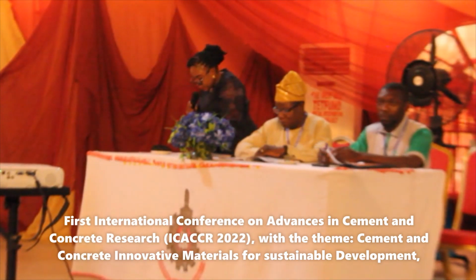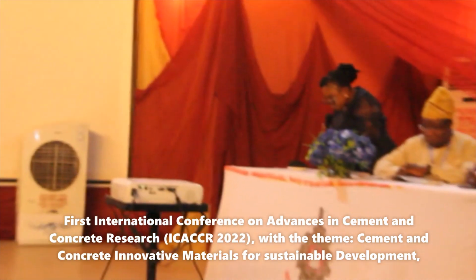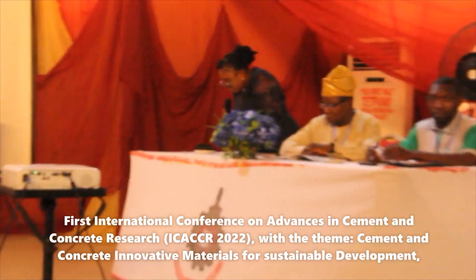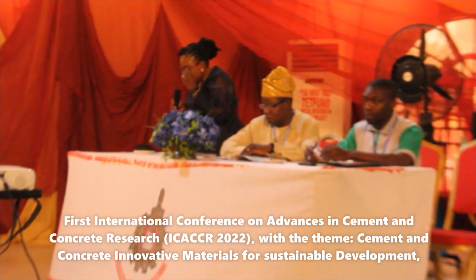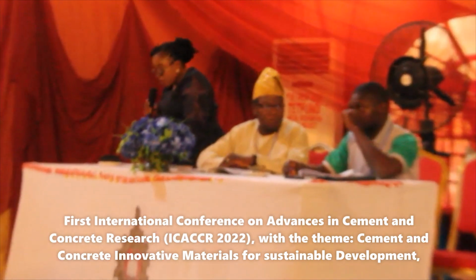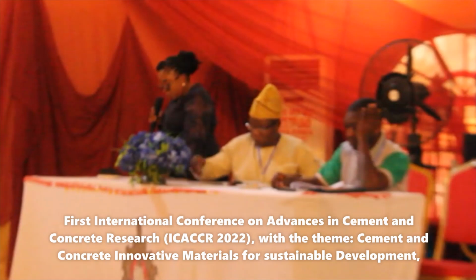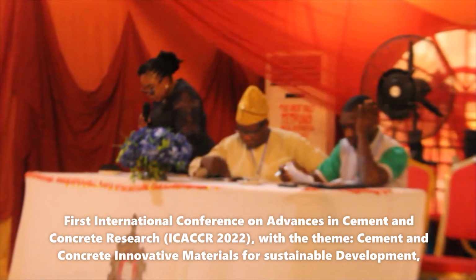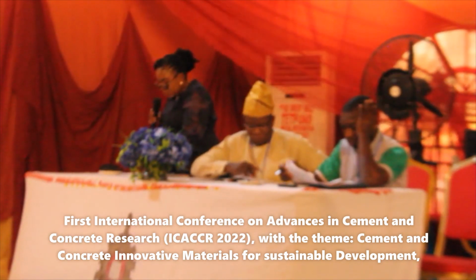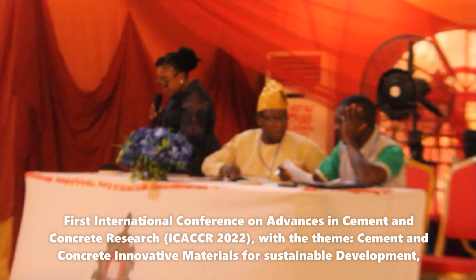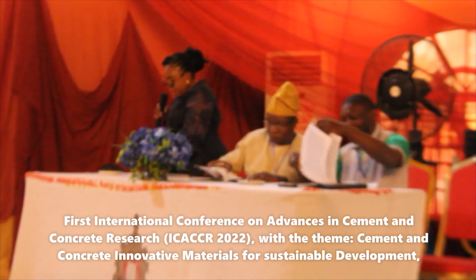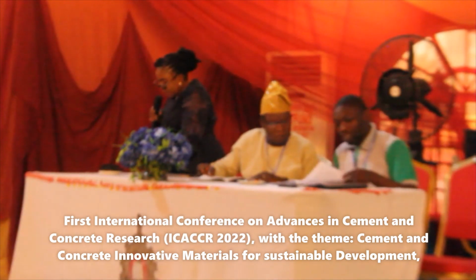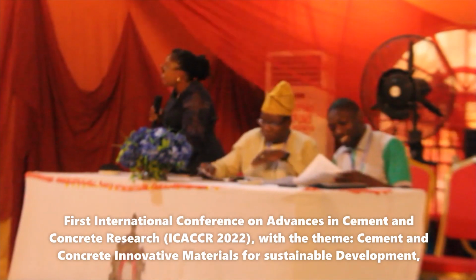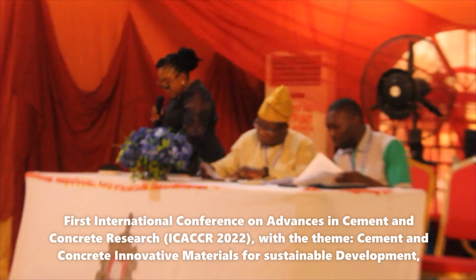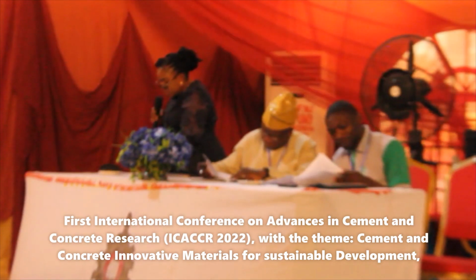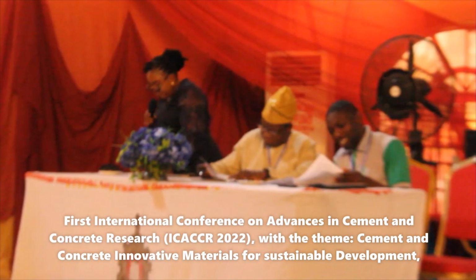Ajayi, presenting a paper titled Mitigation of Alkali-Silica Reaction in Concrete Pavement using supplementary cementitious materials. From his presentation, we understood that the reactivity of the concrete was determined using experimental and statistical methods and modeling. Findings indicate that utilizing supplementary cementitious materials to minimize the ASR reaction in concrete is effective and has a considerable impact on ASR.